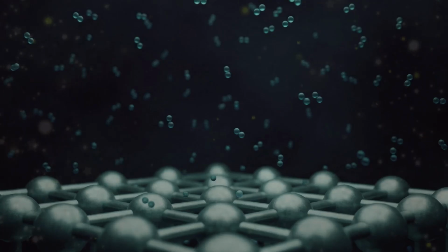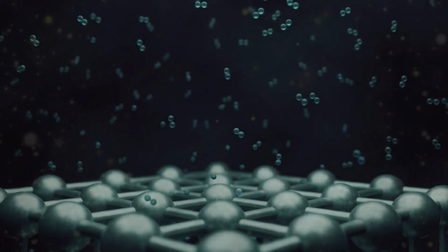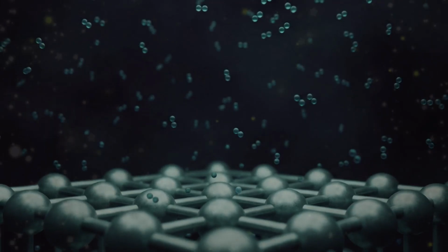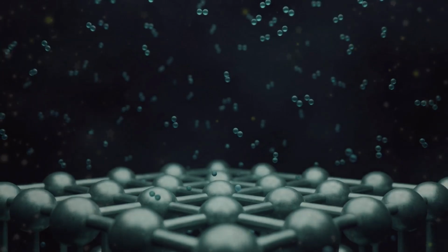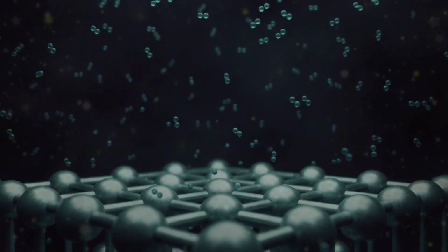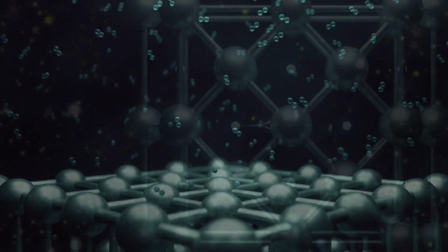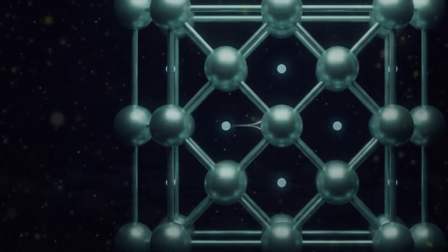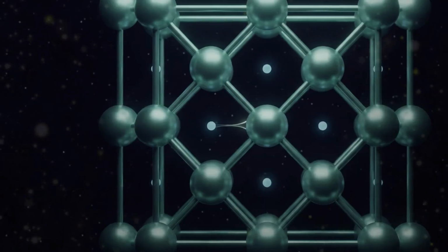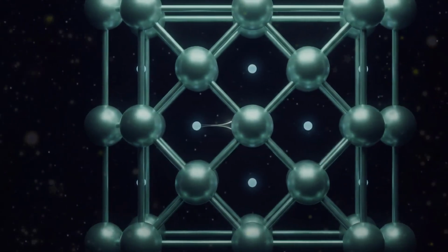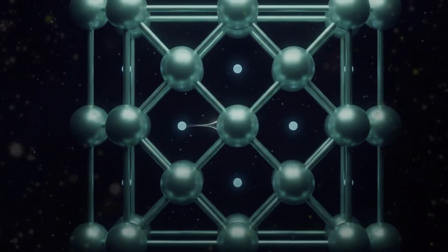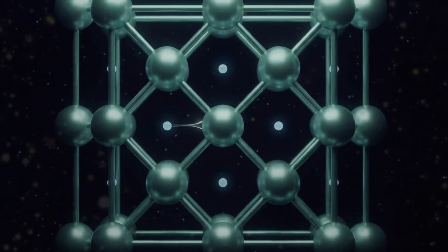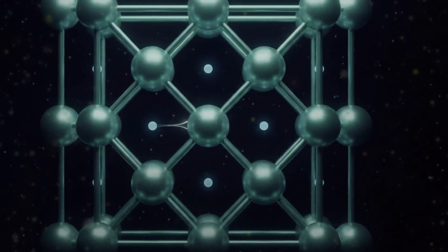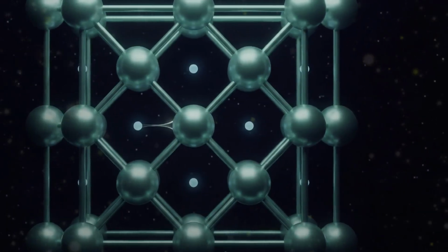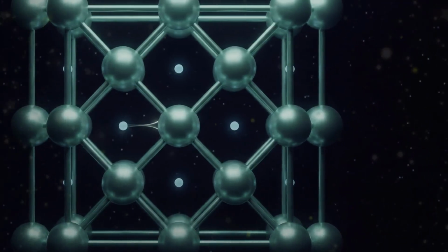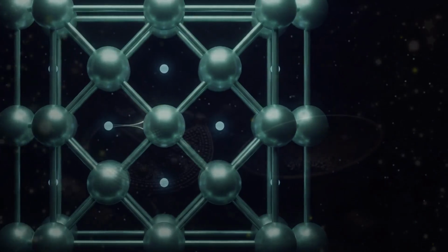Palladium, unlike its platinum group relatives, possesses an unusual chemical property. It absorbs hydrogen gas with extraordinary capacity. At room temperature, palladium metal can absorb up to 900 times its own volume of hydrogen gas. Hydrogen atoms occupy interstitial sites, the spaces between metal atoms, within the face-centered cubic palladium lattice, without fundamentally disrupting the crystal structure. The hydrogen atoms within the lattice retain a degree of mobility, diffusing through the metal along interstitial pathways. This property has been extensively studied in material science research related to hydrogen storage applications.